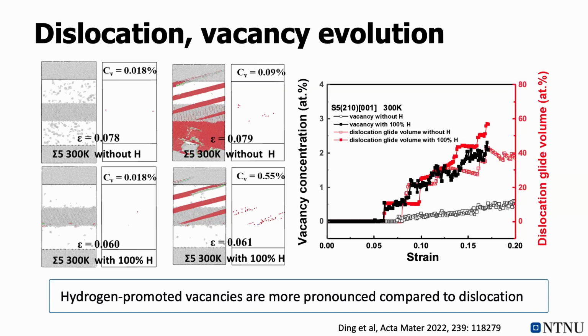And if we look at the snapshot from my simulation, it's also clear that without hydrogen, when the first dislocation emission happens, the vacancy concentration is about 0.09%. But with hydrogen, first, the plasticity onset happens much earlier. If we compare at this strain level, the vacancy concentration is also much higher compared to the hydrogen-free case. This further demonstrates that hydrogen promoted the vacancy behavior, which contributes to the dislocation behavior and to this transition.